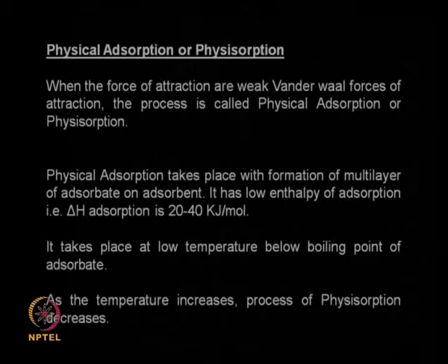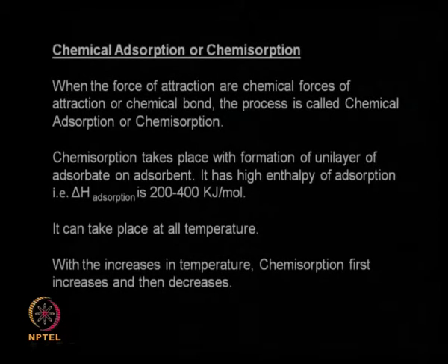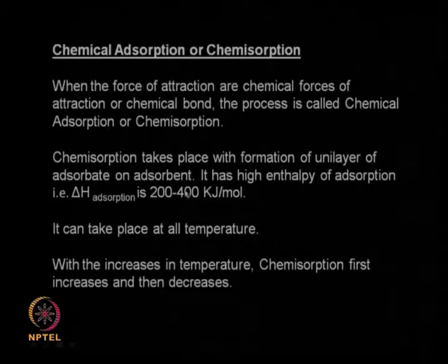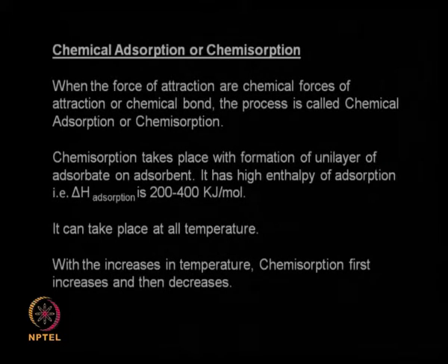As you keep raising temperature toward the boiling point, physisorption keeps going down, and that is when chemisorption happens. Chemisorption is chemical adsorption — here the forces of attraction are chemical bond-type forces, whereas in physisorption you have weak van der Waal forces. In chemisorption, generally a unilayer of adsorbate is formed on the adsorbent, and the enthalpy is very high — 200 to 400 kJ/mol. Chemisorption can happen at all temperatures, and with increasing temperature, chemisorption first increases and then starts decreasing, whereas in physisorption it keeps going down with increasing temperature.